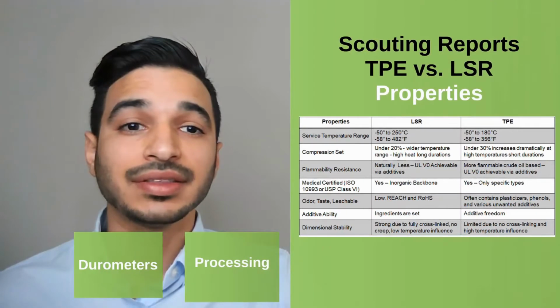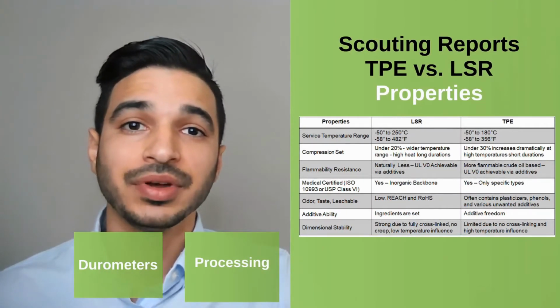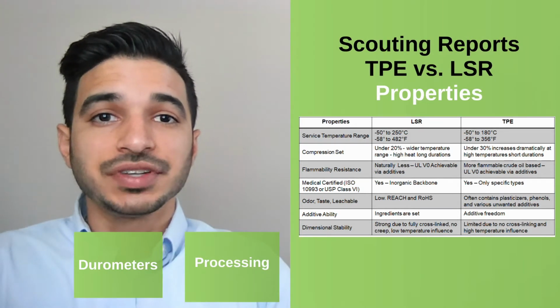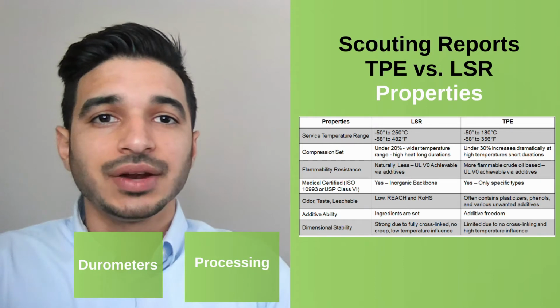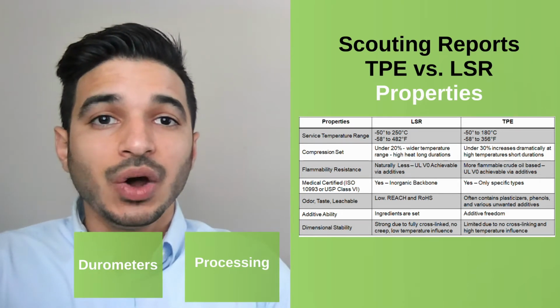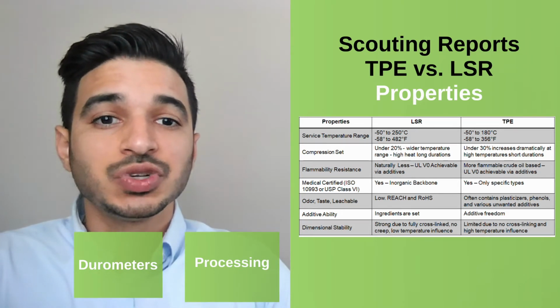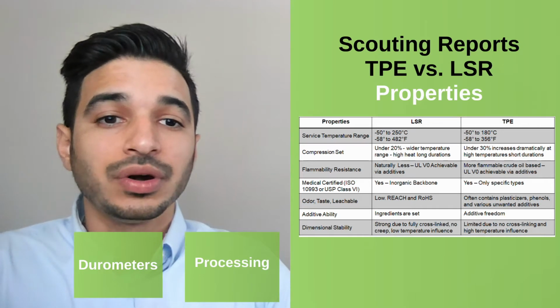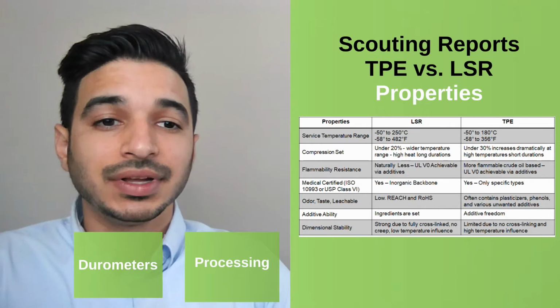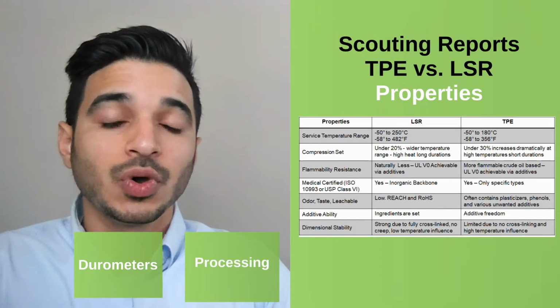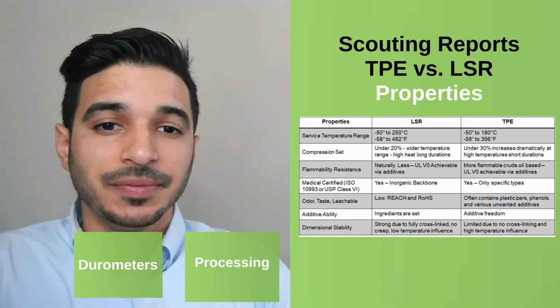Now let's look at the scouting report and compare them, first looking at their properties. Let's start off by comparing the service temperature range. This is a range of temperatures where the materials can withstand without degrading mechanically or chemically. LSR and TPE match up quite well at the low end. However, LSR is able to achieve 250 degrees Celsius or 480 degrees Fahrenheit at the high end, whereas TPE is limited typically to 180 degrees Celsius or 350 degrees Fahrenheit.